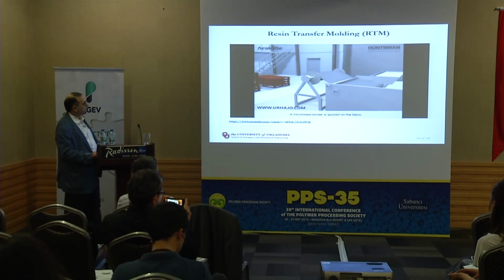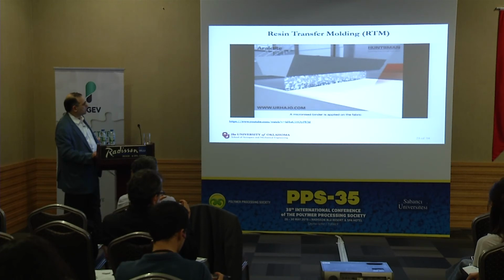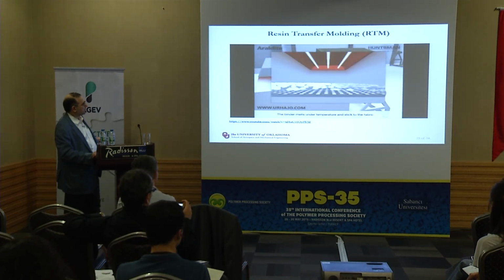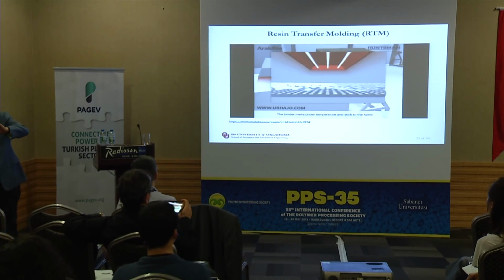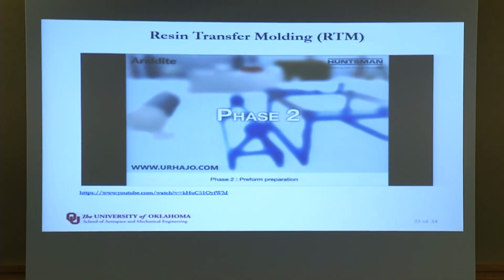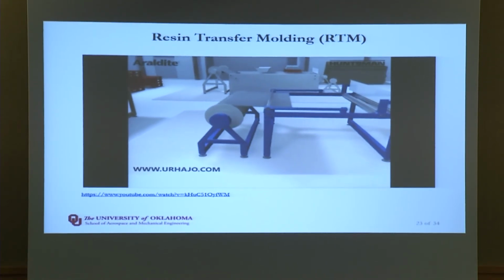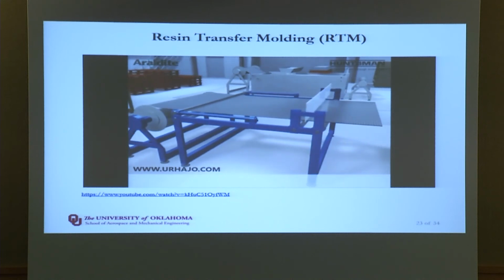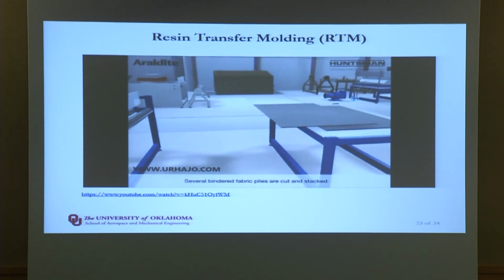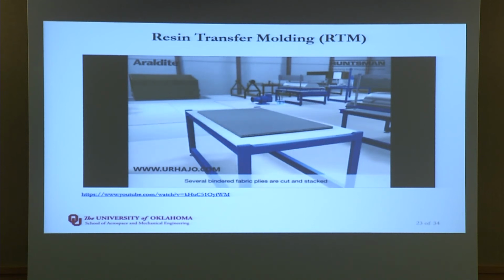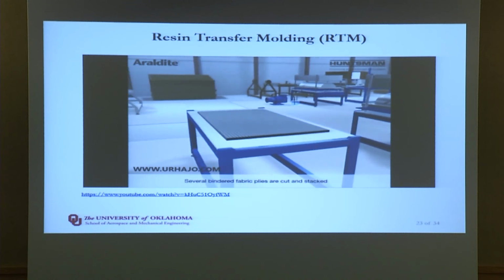So binder application is to prepare the fabric. So you basically would like to apply some kind of binder to the fiber so that once you place multiple layers on top of each other, you have one nice shape to put in the mold. So it's a binder. Preform preparation, so you have your preform here. You would prepare, you cut it to the size, you stack them, you put them on top of each other depending on the thickness of the part you are making. There is a binder so that they don't slide against each other.